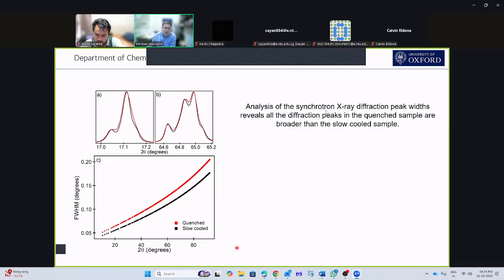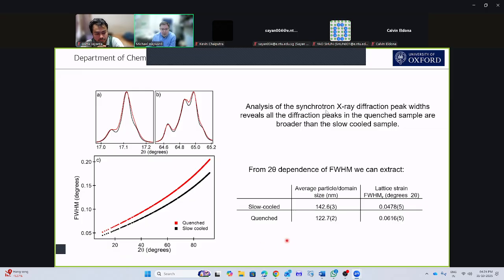And from this evolution in the peak width as a function of 2 theta, we can extract the particle size and the strain from the 2 materials, because that's what leads to peak broadening in the diffraction pattern. And what we see is that the quenched sample, compared to the slow cooled, has smaller particles and a larger degree of lattice strain. And we're going to see that this is what leads to the change in reactivity.